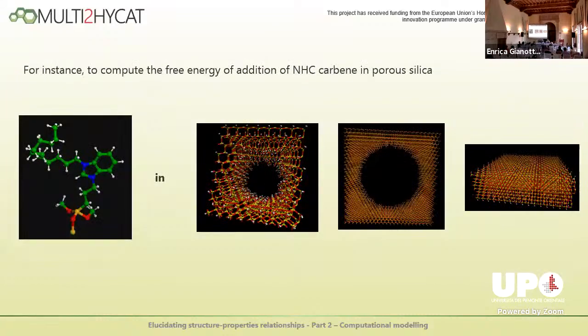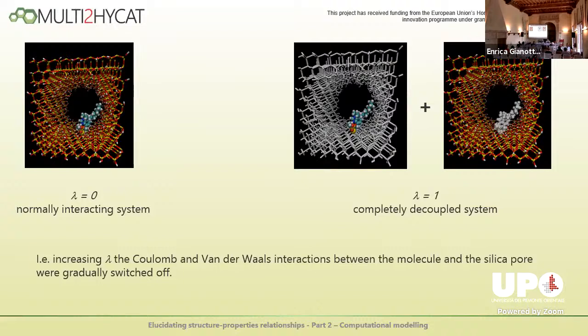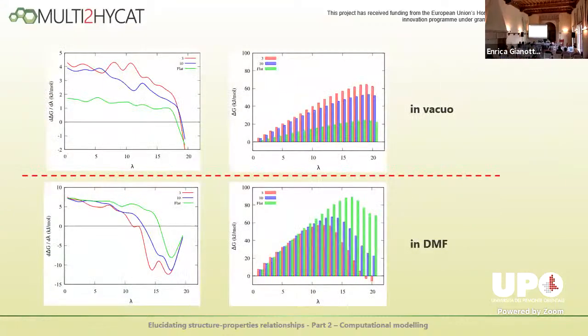For instance, we apply this approach not to the real solvation process, but we wanted to estimate the delta G of formation of a hybrid material in which this carbene catalyst is placed inside some of these porous silica. What we do is we get the real system with the molecule inside the pore, and then we decouple the molecule and the pore. This is lambda 0, this is lambda 1, and then we pass from this situation to this situation by slowly changing the interactions between the molecule and the silica. This is what we get.